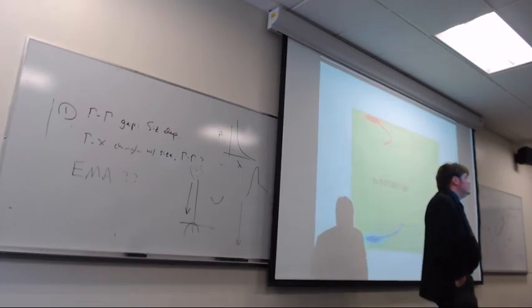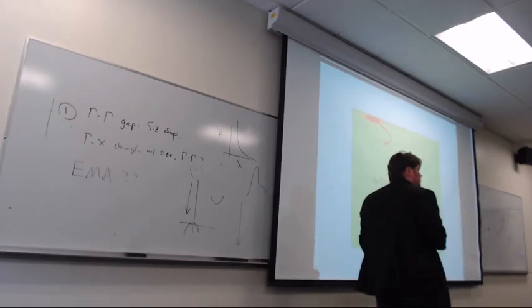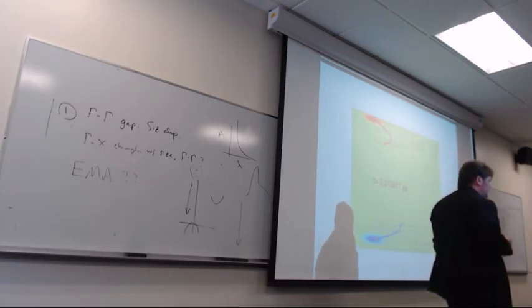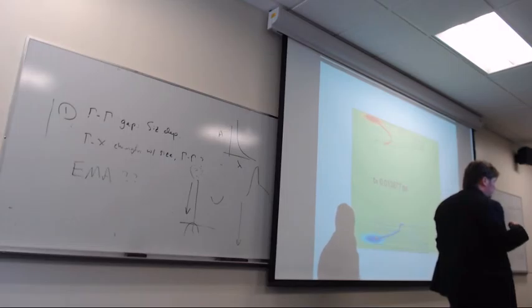Here is the gap. So it's a direct gap in this case. In this case, yes, but it also has an indirect gap. The type, direct or indirect, depends on which crystallographic direction one is looking at. In the 100 direction, it is direct. In 111, it is indirect.